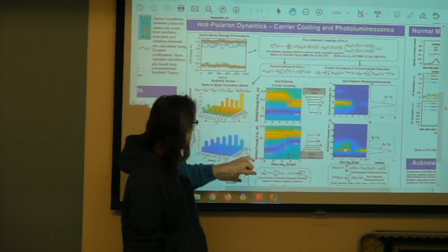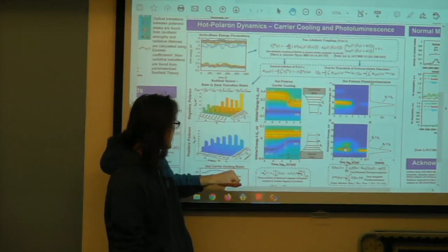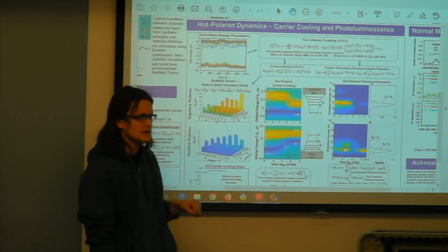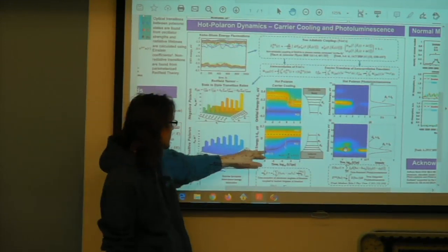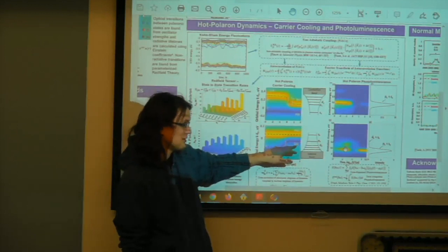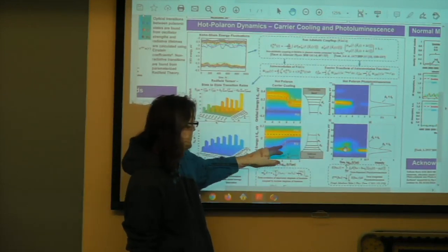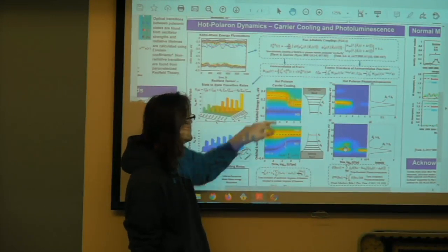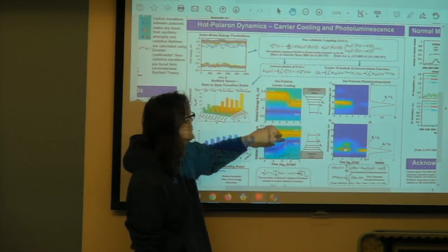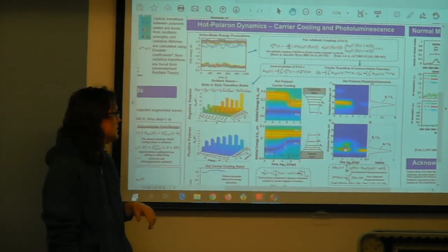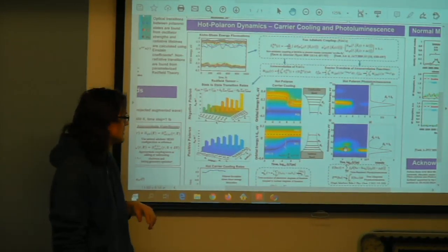And so we do those for both the positive and negative polaron. In this case, we see an interesting contrast in their dynamics. The positive polarons show a pretty single exponential decay, with no kinks as it's relaxing, whereas for the negative polaron, you see something that looks similar to a bi-exponential decay, where there's a mismatch between relaxation rates.